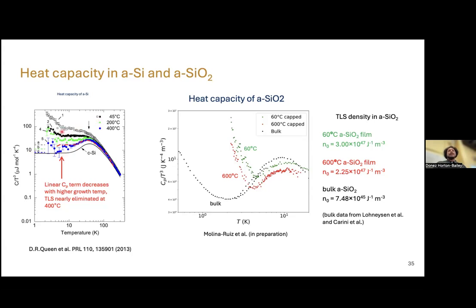But for the actual glassy materials, C divided by T cubed is 1 over T squared. So we should see these things blow up as we get closer to zero, and that's what we see. And based on these heights, we can actually fit the curve and extract the actual values of the TLS density, which I did on the side over here. We saw similar results with amorphous silica. We see that all of these curves start to shoot up as we get closer to zero temperature. If they were crystalline, they would be flat.